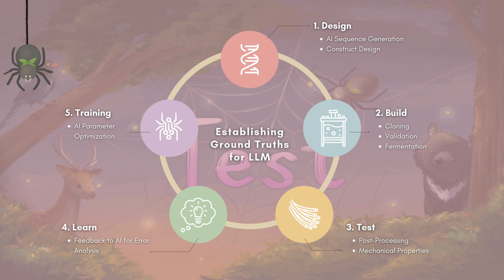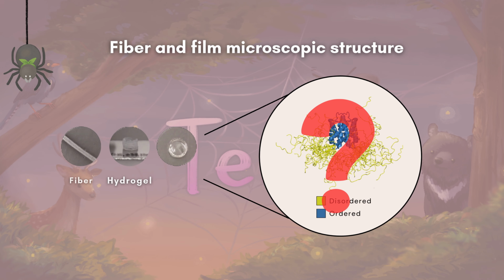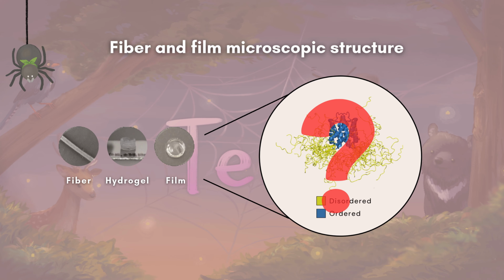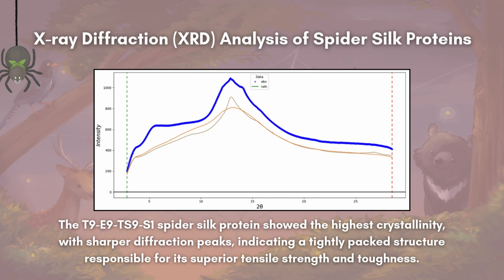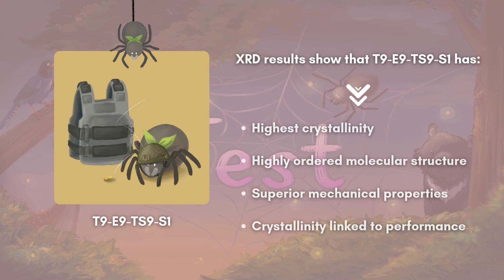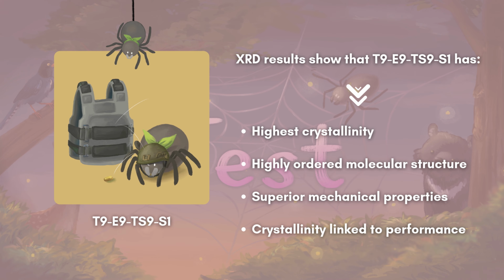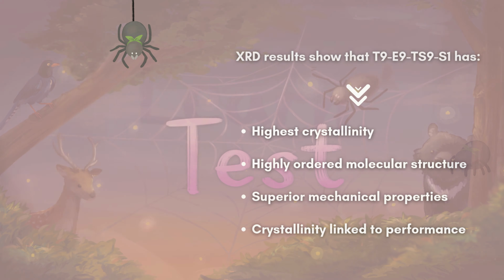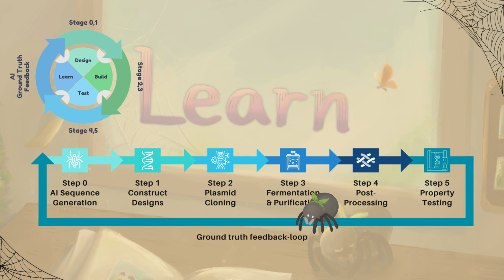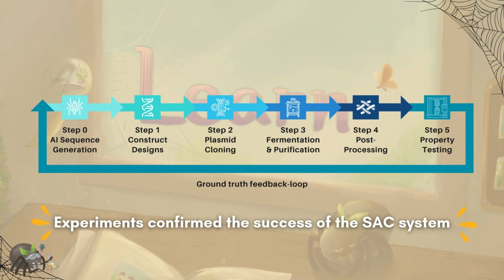We validated our AI model's predictions through tensile testing, providing ground truths for improving our GPSS spider silk sequence generation process. Beyond mechanical testing, we needed to understand the silk's microscopic structure. In XRD experiments, the T9E9TS9S1 spider silk protein displayed sharper diffraction peaks and a higher degree of crystallinity compared to other samples. This suggests a highly ordered and closely packed molecular arrangement, which helps explain its superior tensile strength and toughness. Finally, we've arrived at the learn phase, where we reflect on the insights gained from our experiments. Our experiments confirmed the functionality of the SAC system, from AI-designed sequences to real spider silk materials.